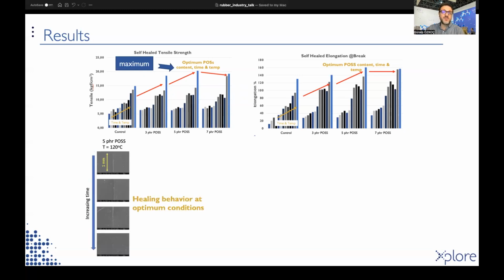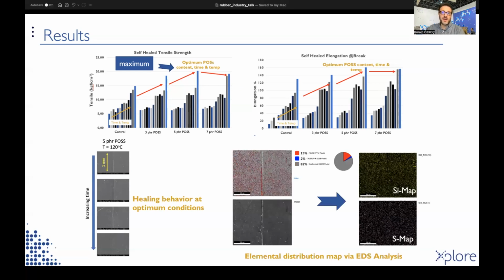SEM imaging studies were performed on the samples having joint surfaces. In these micrographs, you can see that by increasing time, the cut trace was found to be disappeared, indicating that the 2 wound surfaces were conjugated. We also performed an elemental analysis via energy dispersive X-ray spectrometry at the wound site to observe the distribution of the POSS and vulcanizing agents. As you see here, both POSS distribution and sulfur distribution are homogeneous at the wound lips after healing process.